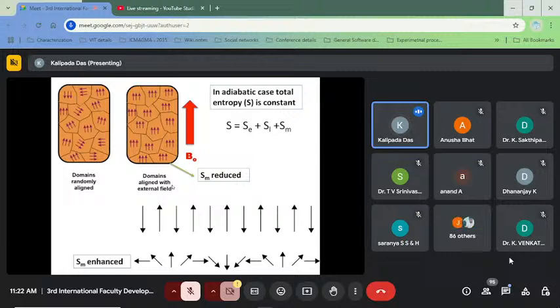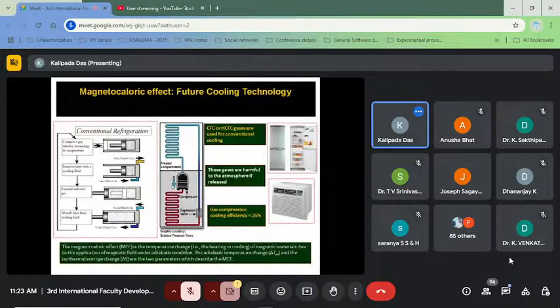Since the domains are oriented along the particular field direction, the entropy should be low in this case. That means to keep the total entropy S of the system conserved, the electronic and lattice parts should be enhanced. That means the system will heat up. This phenomenon was first introduced by E. Warburg in 1881 in the case of iron, and this phenomenon is called the magnetocaloric effect. And this magnetocaloric effect is our future cooling technology.